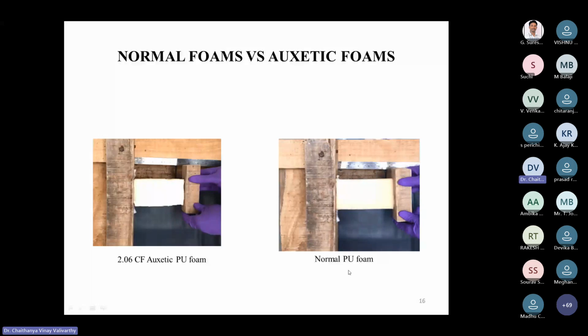As I already mentioned, for normal foams, when you stretch a material in the longitudinal direction, in the lateral direction the size of the foam is reducing. But when it comes to auxetic foam, when you stretch, it is increasing here. If you observe deeply, it is increasing. If I increase the compression factor, this size increase will further increase. So if I increase this compression factor, as you can see here, if you look very deeply, you can understand the difference between normal and auxetic PU foams. Next.